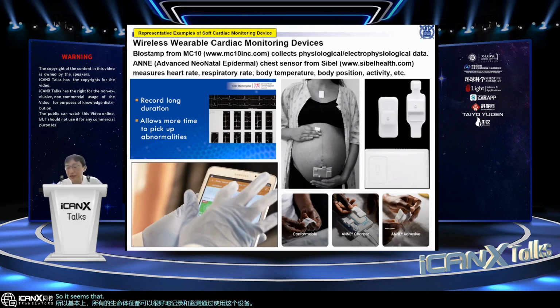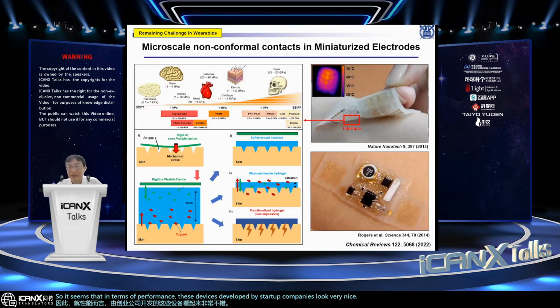So it seems that in terms of performance, these devices developed by startup companies look very nice, but still there is a remaining challenge. The key remaining challenge is microscale non-conformal contacts in miniaturized electrodes. If we take a look at the interface between the flexible device and the human skin, since the human skin has this morphology, some wrinkles and rugged surface, although we make contact between the flexible device and the human skin, there can be some non-contacted region, these air gaps. And due to this air gap, of course, the contact impedance will be high. And if the contact impedance is high, then the signal-to-noise ratio in biosensing will be low.